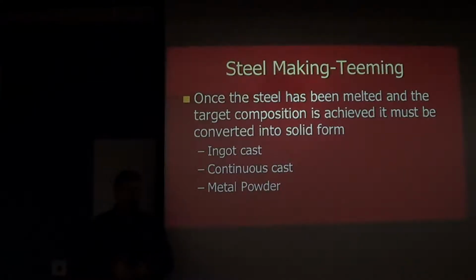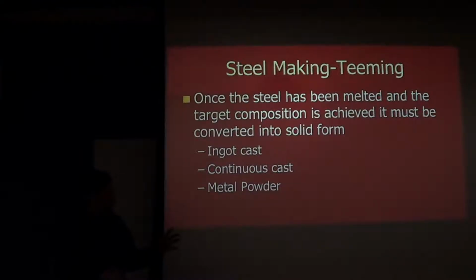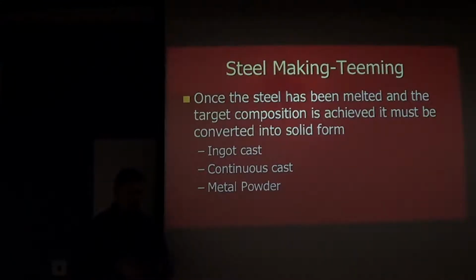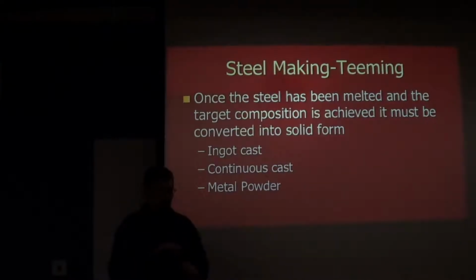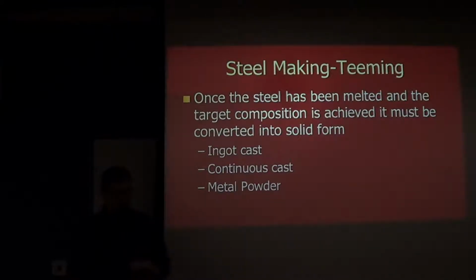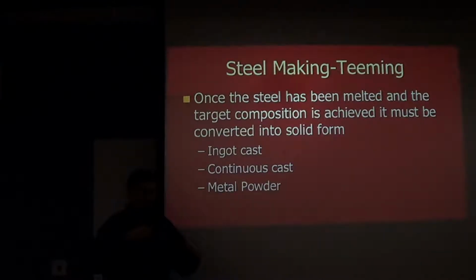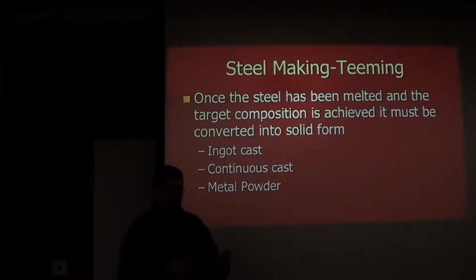Most of what we deal with at Scott Forge is ingots. We do purchase some continuous cast product. I want to talk a little bit about continuous cast here because I neglected to put a good illustration in it. The continuous cast method starts with a copper mold that has a bottom that's held in place by a big hydraulic cylinder. And they don't pour the metal directly into the mold, they'll pour the metal into a giant tub called a tundish.